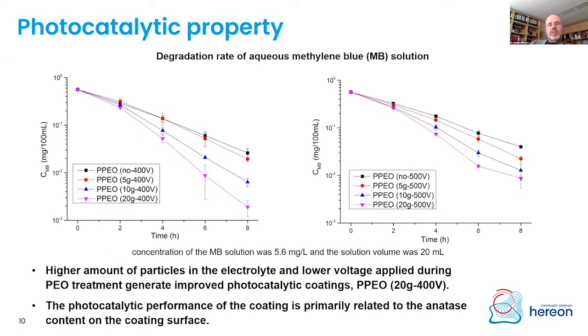So if we now look at the properties which we are obtaining, it is quite nicely visible that we get better performance at those treatments at 400 volts, when we are not destroying too much of the particles which we have added. And there is also a nice trend that with increasing amount of particles, we get a higher degradation rate of methylene blue, which was our model organic dye in the solution, which should be degraded. And you see that with the same processing and the same amount of particles, when you go to 500 volts, you have a much lower degradation rate compared to 400. So basically it all depends on how much of the titanium dioxide we are able to immobilize on the surface, which is then available for the degradation.